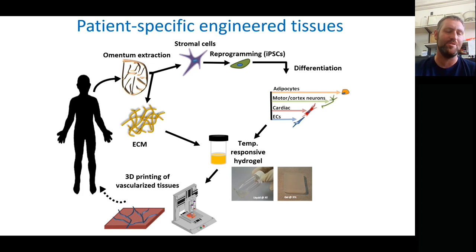The ECM hydrogel is liquid at lower temperatures or room temperature, and at 37 degrees — when incubated at physiological temperature — it becomes a robust solid gel. We're able to print it at a malleable state and then have it solidify afterwards to form the tissue. Before we print, we mix the cells with the ECM so that we have our bioink — a cellularized bioink — in order to print them together.